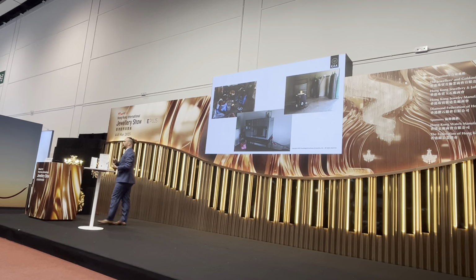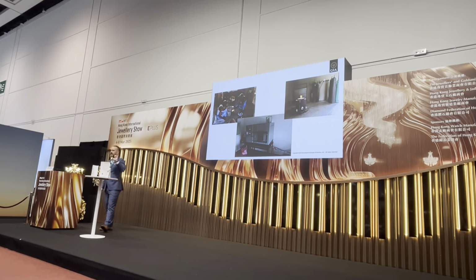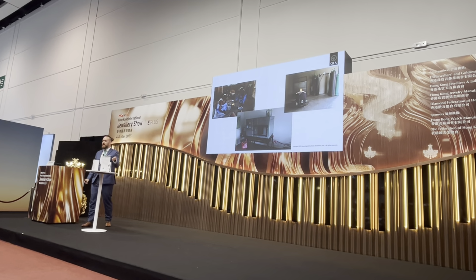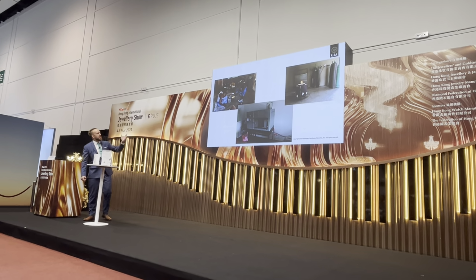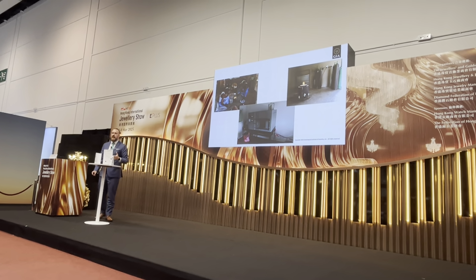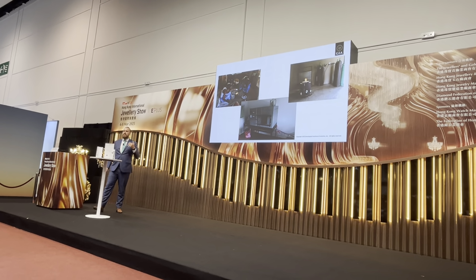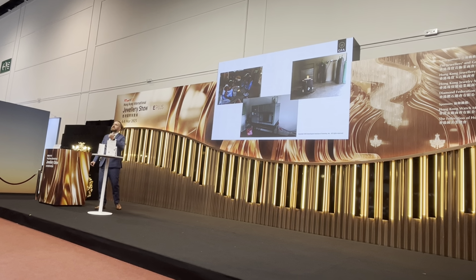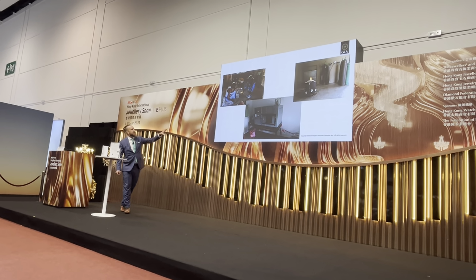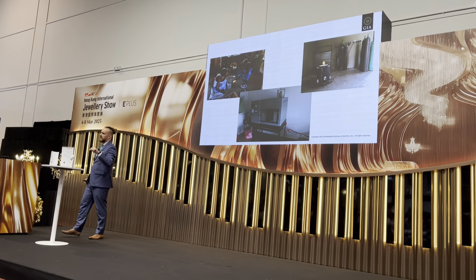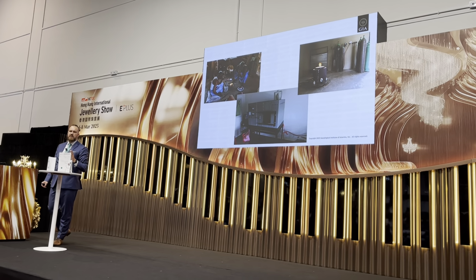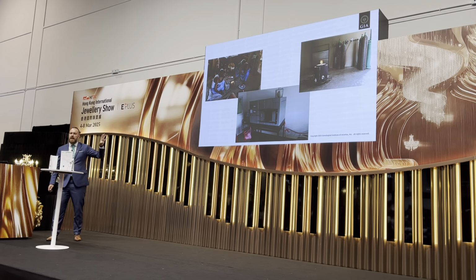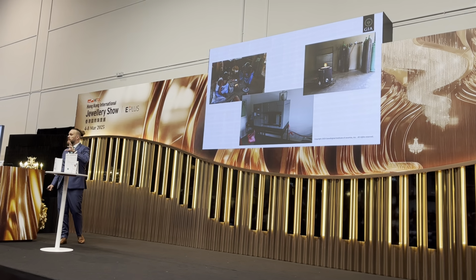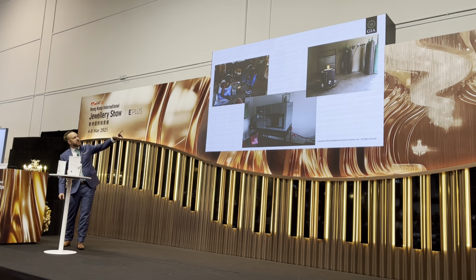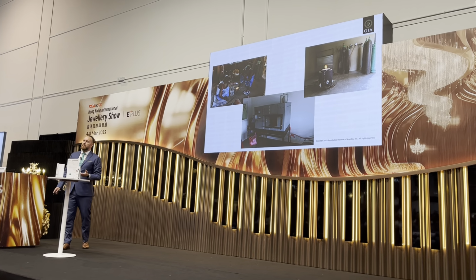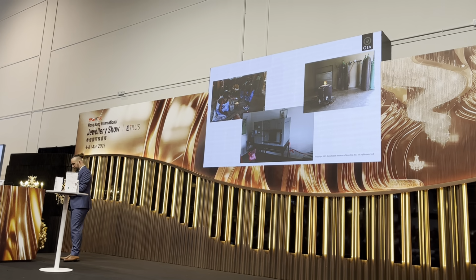Nowadays, most of the treatment happens in a furnace like this, which is an electric furnace with a heating element that has a lot of advantage. You can basically set the temperature, and as long as it's plugged in, it will hold that temperature. The one on the right, it is when your gas runs out, the burn is over. If you want it at 400 degrees or at 600 degrees, it is very difficult to control that. The furnace on the bottom, you can set it at 1648 degrees, and it will be 1648 degrees. So that is why a lot of people still prefer that furnace as well. But there are still people that are using the traditional burn, because that picture on the top right is a picture I took 6 months ago. So people are still doing it that way.